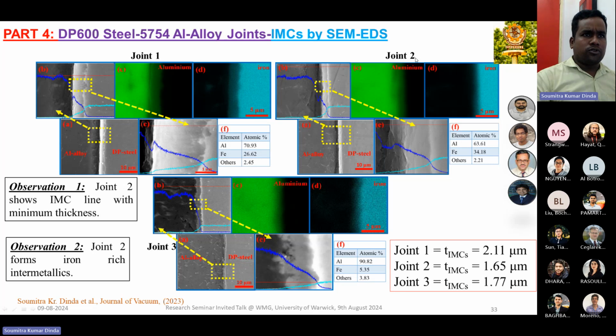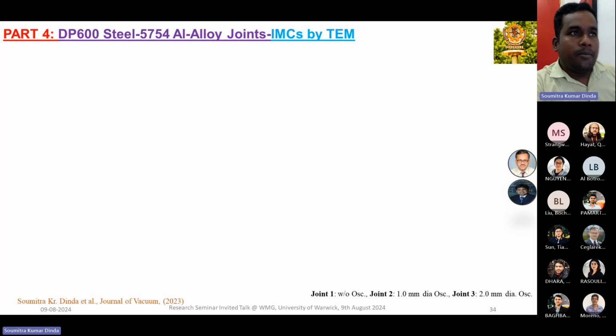Now similarly we did it for joint 2 and joint 3. Now if you compare this one and this one, check the slope. This slope is maximum for joint 3, and also we can see the thickness. From joint 1 to joint 2, the intermetallic layer thickness decreased from 2.11 to 1.65 micron, and it again increased to 1.77. That means in case of joint 3, instead of getting superior property, we are getting bad property from the defect point of view. Then we did TEM for the intermetallic visualization, that is the transmission electron microscopy.